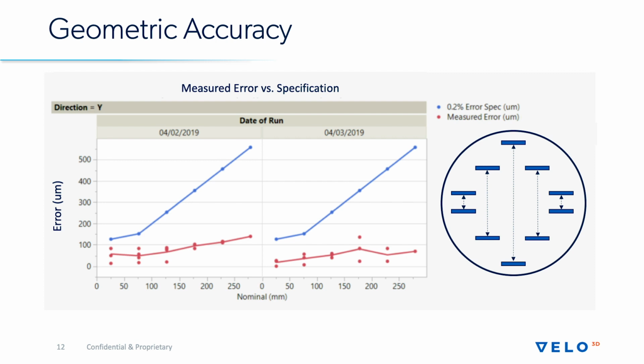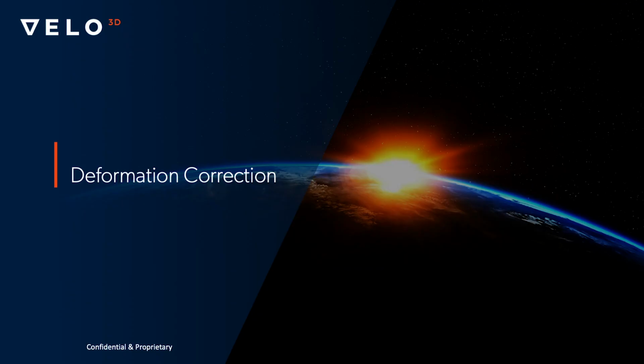And what you can see is that the blue line is that 0.2% spec line, and the red line is what we're actually achieving. So even when you're using the entire build area, so have parts that are 300 millimeters apart from each other, the overall error in their placement is still less than 150 microns by using this in situ capability. The last thing I want to talk about is deformation correction.